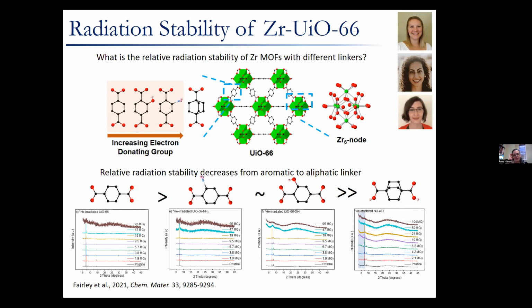At the bottom of the screen, you can see the powder X-ray diffraction results. I know you can't see all of it, and that's not really the point. The point is that we studied these different zirconium MOFs with the different linkers as a function of dose, all the way from no dose up to 95, or in the case of the aliphatic material, up to 104 megagray. What you need to be paying attention to is whether the line looks pretty flat and there are nice distinct peaks, which tells us it's a crystalline material, versus whether the data is very noisy and has these very large humps, because that is indicative of an amorphous material and therefore degradation of the MOF itself.